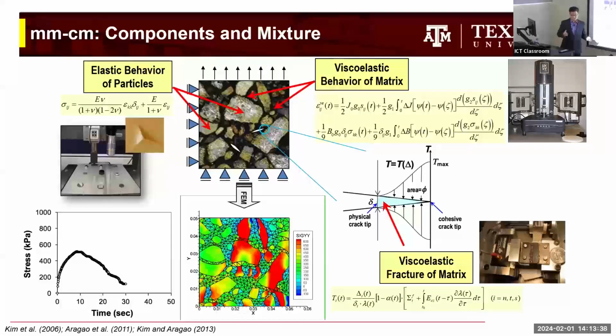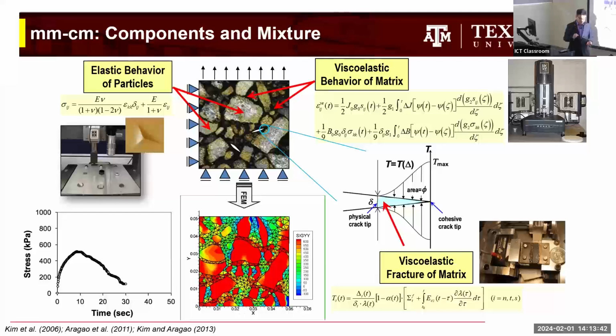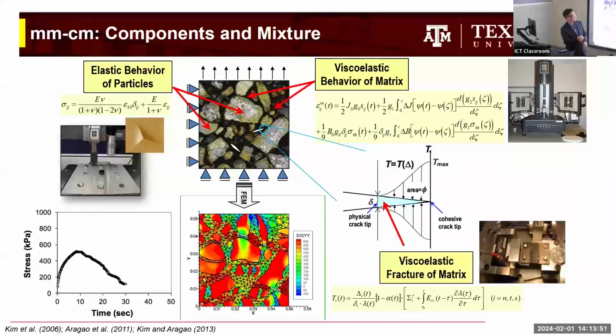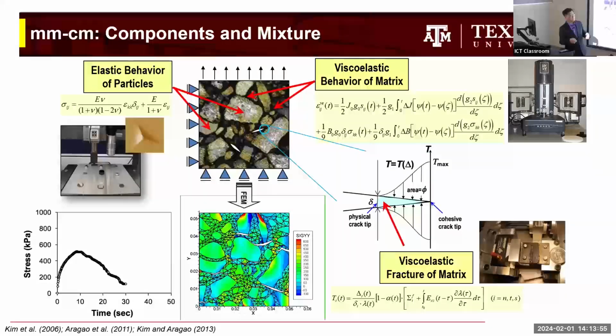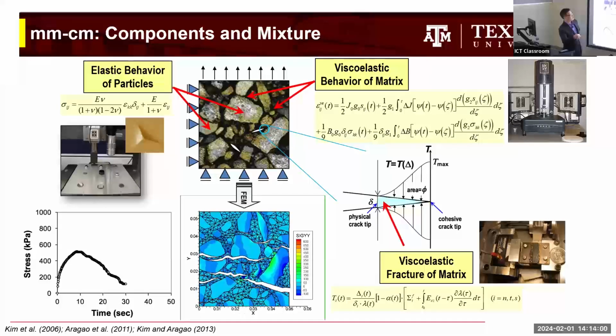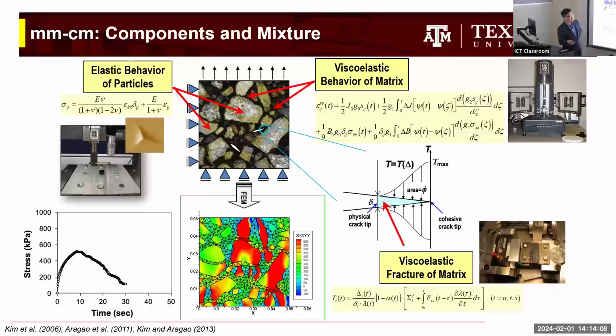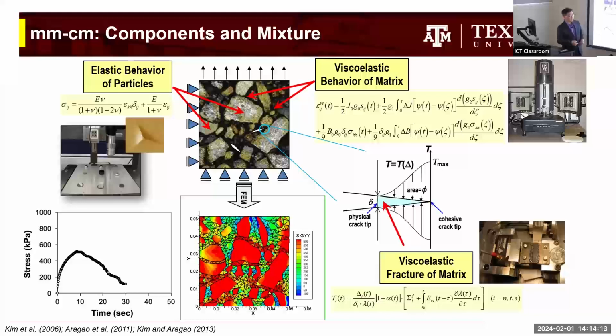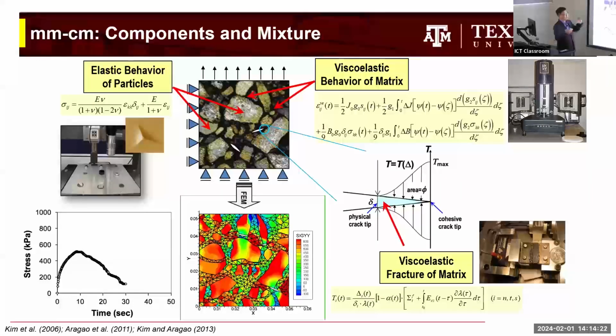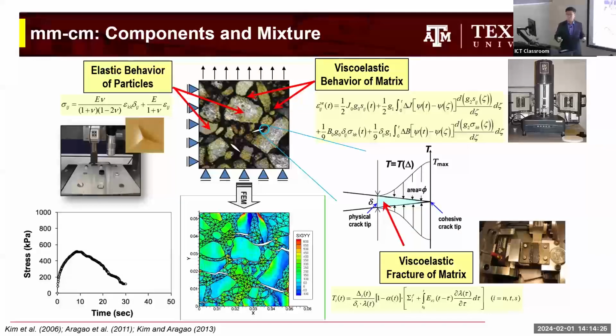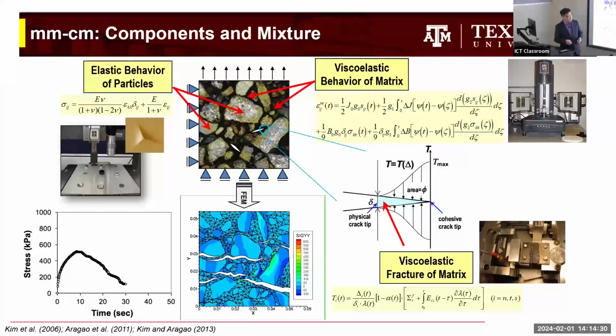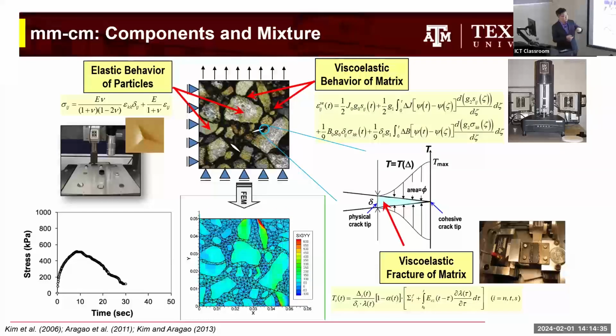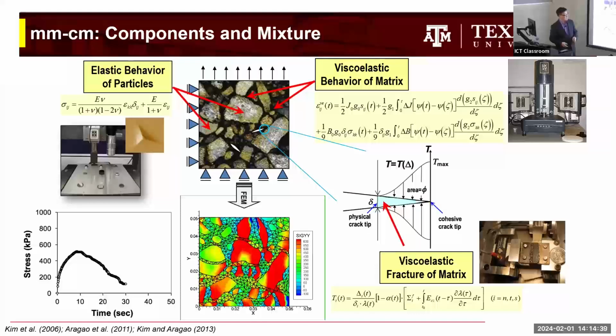And then we also worked on modeling of mixtures, which is like composite mechanics. You are familiar with that, I believe. For a given mixture level, let's say asphalt concrete, you have particles, like rocks, and fine matrix. When we characterize the particle property and the matrix property, let's say viscoelasticity, we allow cracking of the matrix that we see from testing. So we adopted a cohesive zone fracture model to model crack initiation and propagation, and elasticity for the aggregate. We combine all together in finite element modeling. I know some of you are very familiar with FEM and have made excellent efforts on that, and interestingly, we can simulate mechanical testing using this computer simulation. And here are the results coming up.